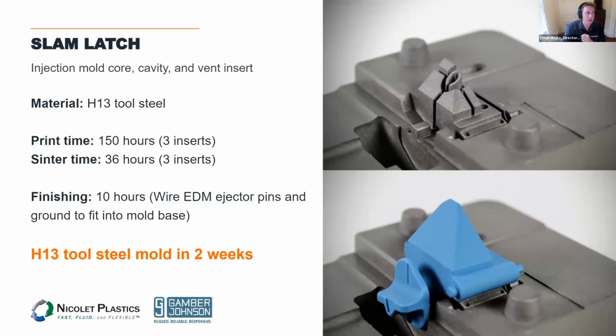So they went ahead and printed 3 different components here: a core, a cavity, and a vent insert that went inside of this little pocket here to allow for some venting. The print time was 150 hours, so about a week for all three inserts. And then all three inserts can go into the furnace together for about 36 hours. After printing was complete, this insert took about 10 hours of final finishing, wire EDM of the ejector pins, and then some grinding just to fit it into the mold base. So ultimately, they were able to deliver an H13 tool steel mold in just 2 weeks.